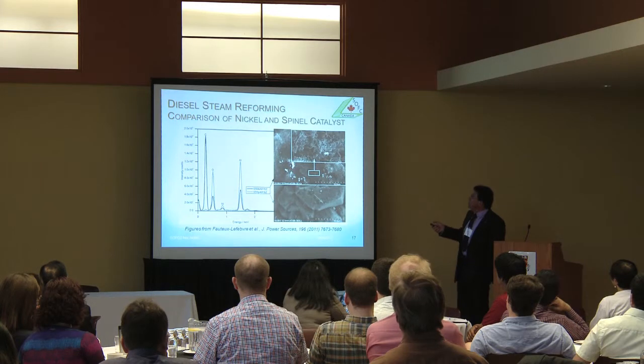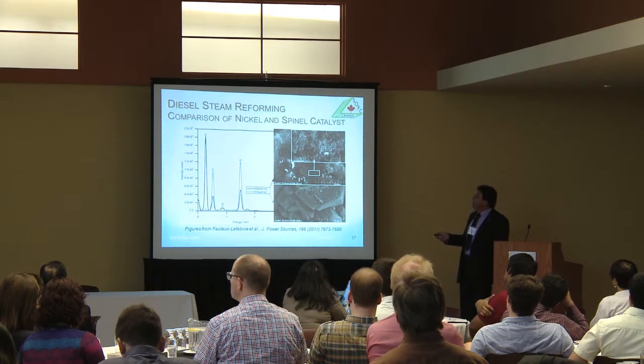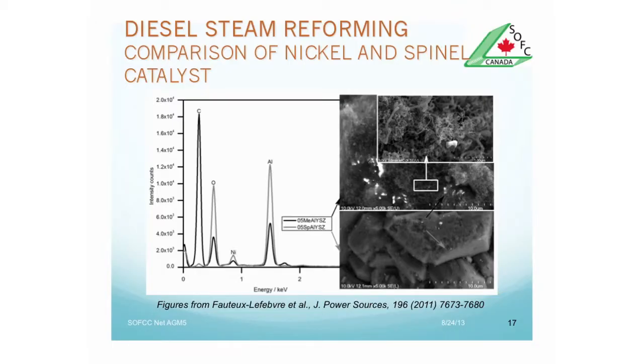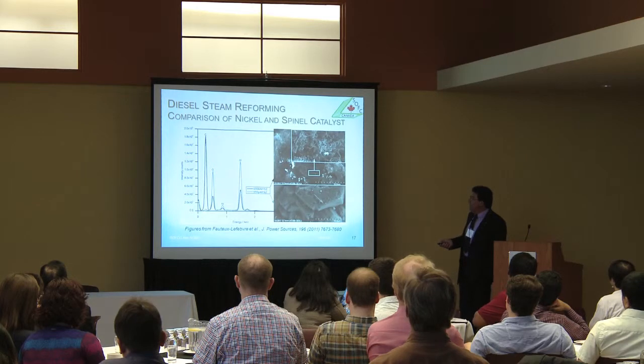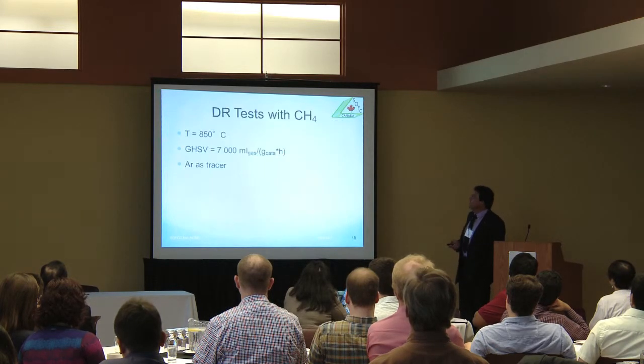And if we go to scanning electron microscopy coupled with EDX, we clearly see that there is filamentous carbon formed on the nickel, not on the spinel, and we clearly see the carbon signal, which is nonexistent in the case of the spinel.